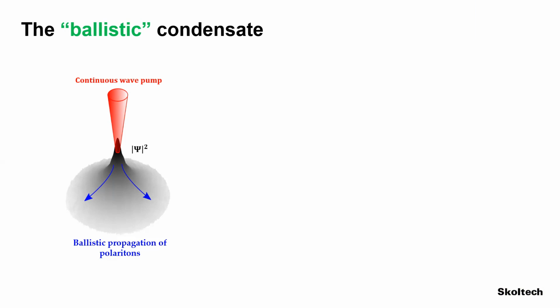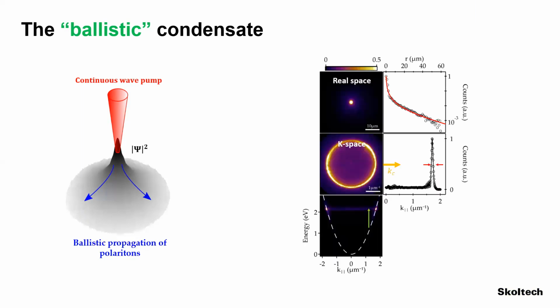or an external reservoir, and I get, with a gray dashed line here, the density of polaritons. And if I go above threshold, I get a polariton condensate. If I look at real space, it looks like a laser. I have a very bright spot. If I do some careful analysis of the decay, I see that polaritons propagate in the plane of the cavity in all directions, and I have an exponential decay. It's actually the Hankel function.